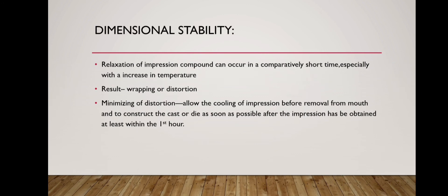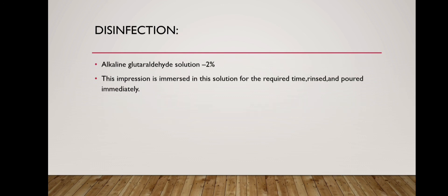Dimensional stability: Relaxation of impression compound can occur in a comparatively short time, especially with an increase in temperature, resulting in warping or distortion. To minimize distortion, allow the impression to cool before removal from the mouth, and construct the cast and die as soon as possible after the impression has been obtained — at least within one hour.